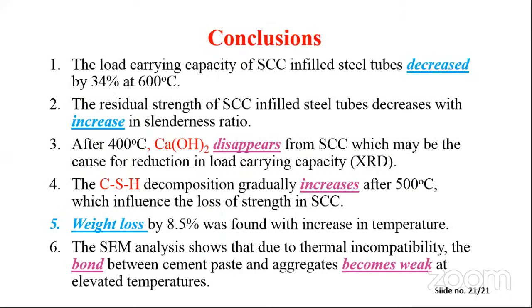So these are some conclusions drawn based on the study. The load carrying capacity of self-compacting concrete decreased by 34% at 600 degrees centigrade, and with increasing slenderness ratio, residual strength is decreasing. Calcium hydroxide is disappearing at 400 degrees centigrade, whereas CSH gel, developed in the dehydration process, decomposes gradually and increases after 500 degrees centigrade, which influences the loss of strength in SCC. Weight loss of 8.5% was found with increasing temperature.